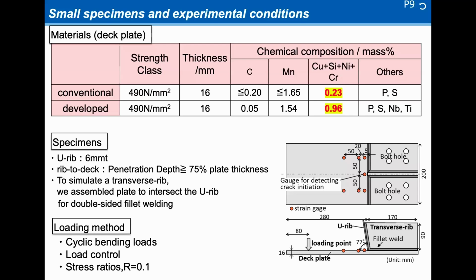Materials: the deck plate is conventional steel or developed steel. Strength class is 490 N/mm² and 16 millimeters thick. As explained at the beginning, a large amount of solid solution strengthening elements such as copper and silicon is added to the steel component of the developed steel. The U-rib is 6 millimeters thick and the rib-to-deck joints were welded so that penetration depth becomes 75% or more of the plate thickness. Loading method: cyclic bending loads, load control, and stress ratio is equal to 0.1.